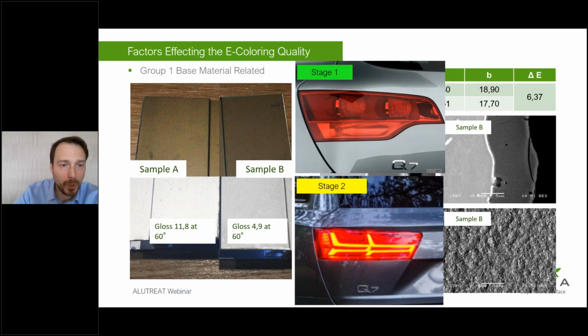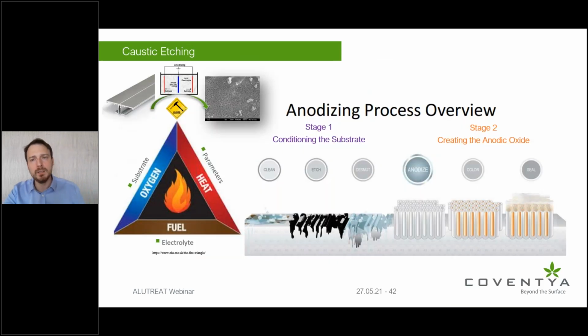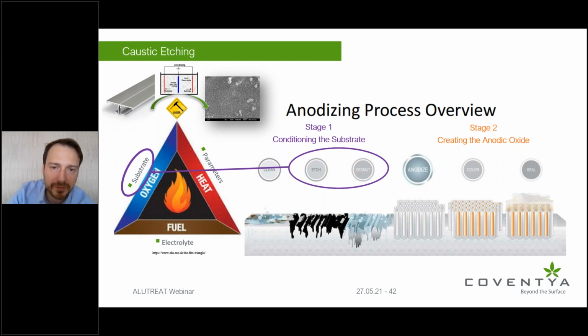So same example, what can we do in order to have a better underlying substrate or a better layer is, quite frankly, relatively easy. That's the topic of pretreatment. So we need to have the right substrate and the right surface with the right roughness and also distribution of the alloy, so that we have the base, which is uniform and much more suitable to grow our anodic oxide, which will be then the template for our coloring.